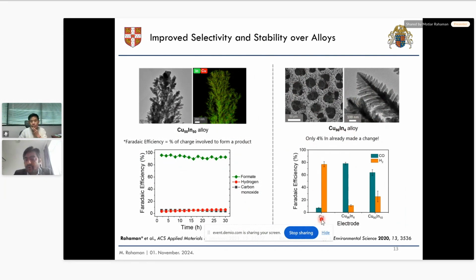We can see here pure copper with a similar structure, at low overpotential. We have to note that these experiments were done at a very low applied overpotential, where copper gives only hydrogen and is not much active for the carbon dioxide conversion process. But if we use this copper indium with 4% added indium, the scenario completely changes. It swaps the product distribution. From close to 80% hydrogen, we get around 80% carbon monoxide as a carbon dioxide conversion product. So this 4% indium makes the catalyst really active for carbon dioxide conversion at very low overpotential. So apart from morphology, the composition of the catalyst is also very important in electrocatalysis to drive carbon dioxide conversion selectivity into valuable products.